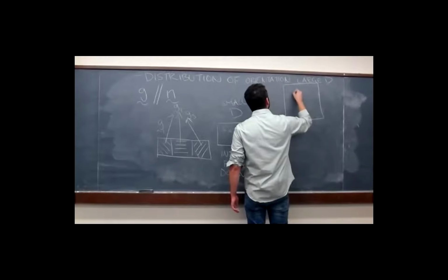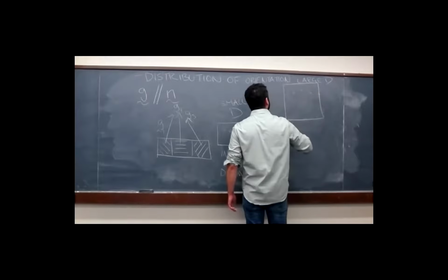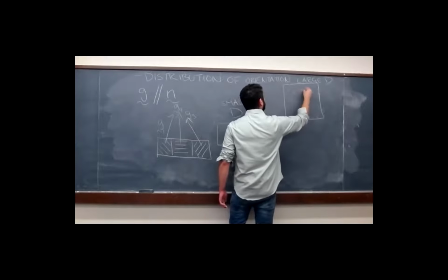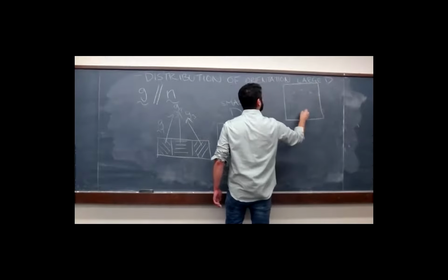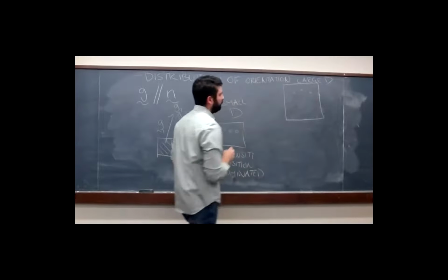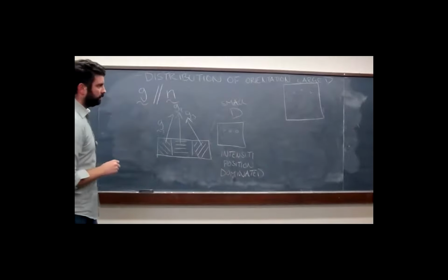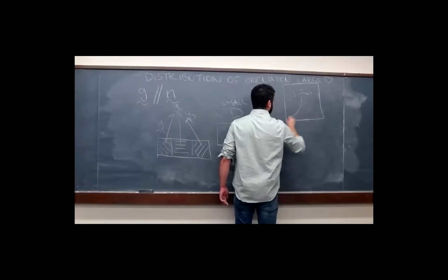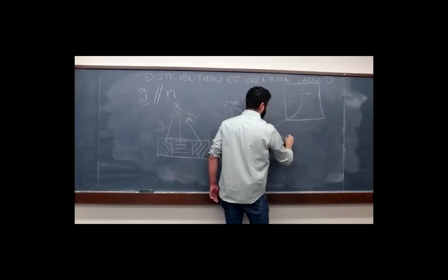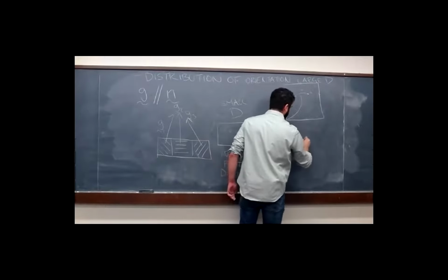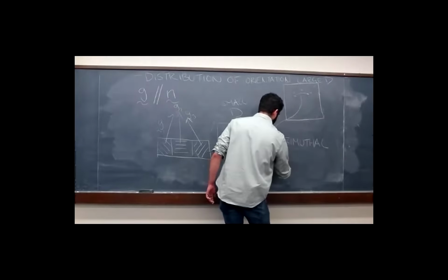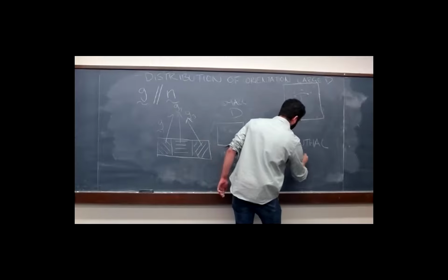Now, in the far field, the diffracted intensity will show up in very different positions on the detector. The intensity will show up at a fixed radial position on the detector, but what we're going to get is azimuthal or misorientation broadening.